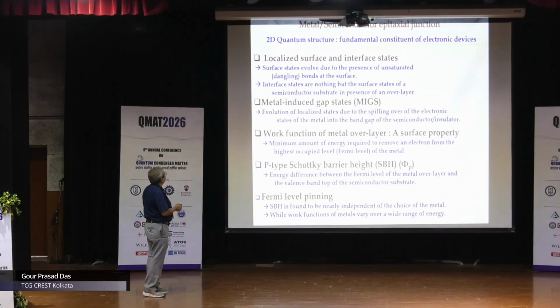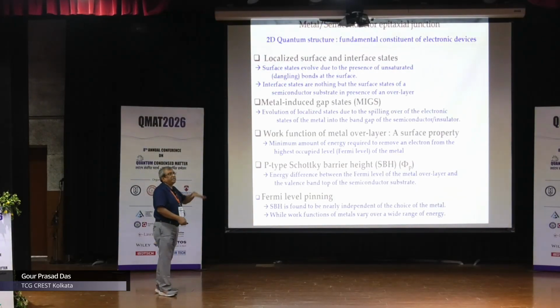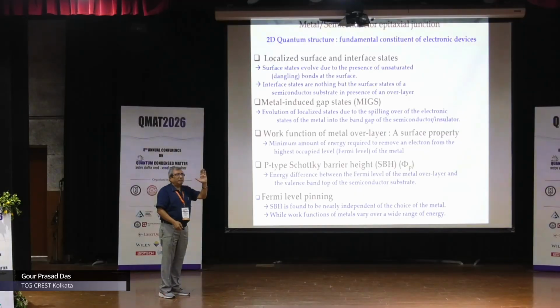Okay, now the metal-semiconductor epitaxial junctions: I would like to tell you that these are 2D quantum structures, and they are the fundamental constituents of electronic devices. The most important things as far as the physics of these quantum devices are concerned are given here: 1, 2, 3, 4, 5. Localized surface and interface states. The surface states evolve due to presence of unsaturated dangling bonds at the surface. And interface states are nothing but the surface states of a semiconductor substrate in presence of an overlayer. Metal-induced gap states: Volker Heine talked about this in the 60s. So, the evolution of the localized states is due to spilling over of the electronic states from the metal Fermi sea to the semiconductor band gap.